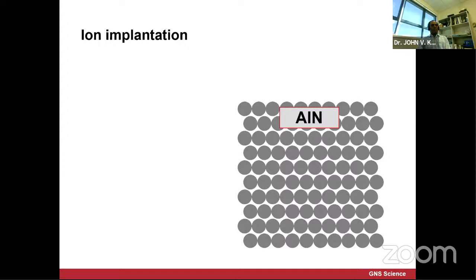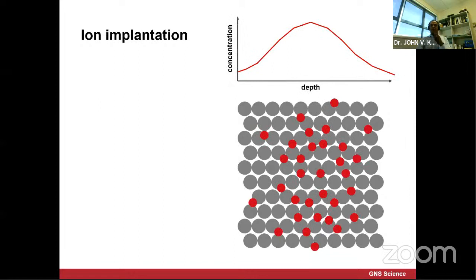In this case, I think some of you may not know what ion implantation is. Ion implantation is a well-known technique used in the semiconductor and microelectronics industries to dope impurity ions to change the functionality, like electrical, optical, and magnetic properties, and so on. Let's say you have aluminum nitride crystals, and an ion goes in and sits as an impurity in the lattice sites, and some of them go into the vacancies. Depending on the incident ion energy, you can modify the surface or dope at a certain depth. You can also determine what concentration of ions you dope. So that's the kind of thing people do.